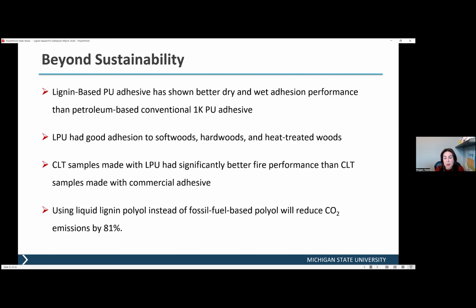To summarize, this lignin-based adhesive is going to go beyond just being sustainable. As I showed, the lignin-based polyurethane adhesives have better dry and wet adhesion performance compared to the petroleum-based conventional one-component polyurethane adhesives. They also had really good adhesion to softwoods, hardwoods, and heat-treated woods. The CLT samples that we prepared with the lignin-based polyurethane adhesives had significantly better fire performance than the commercial adhesives. What we found through the life cycle assessment is that using liquid lignin polyol instead of fossil fuel-based polyol to make polyurethane adhesives is going to reduce CO2 emissions by 81%.